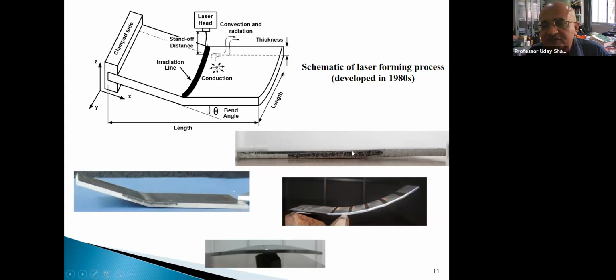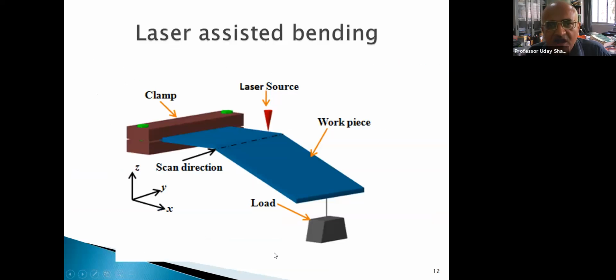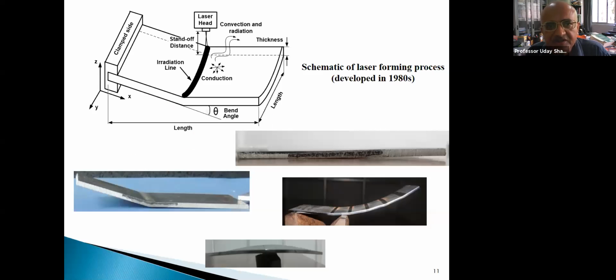Even this is a brittle material which has been bent by laser forming, because due to temperature its nature got changed. If I do it at cold temperature, then there will be cracks. And then I am making different types of shapes. I can make a cup, in fact, and this was just by heating. There is no contact at all. You can do that forming during or after the assembly also. In any inaccessible area, you cannot take your whole machine and die and punch, but you can take your laser torch there, and it can be done.